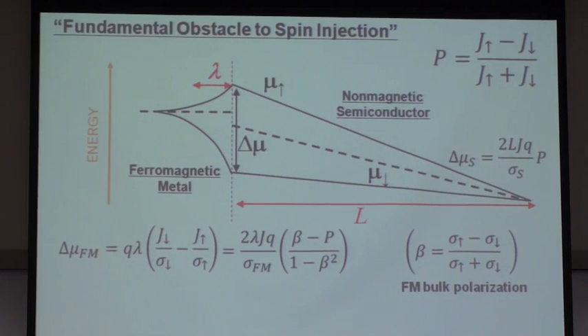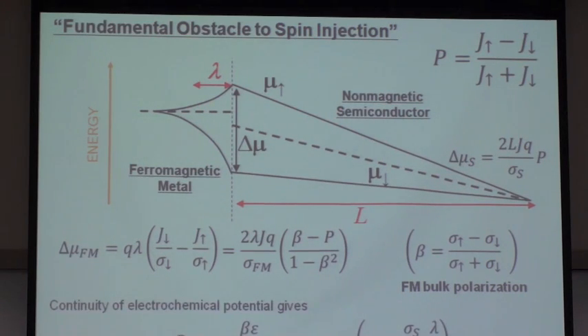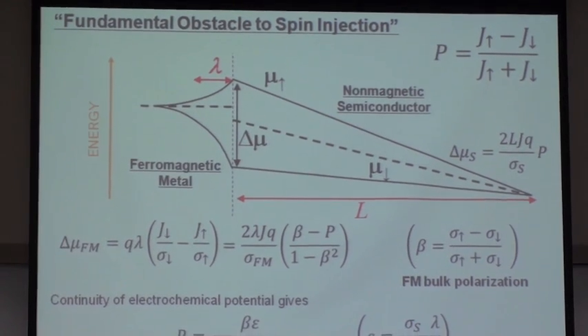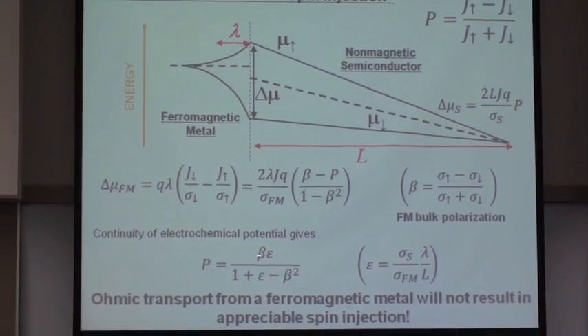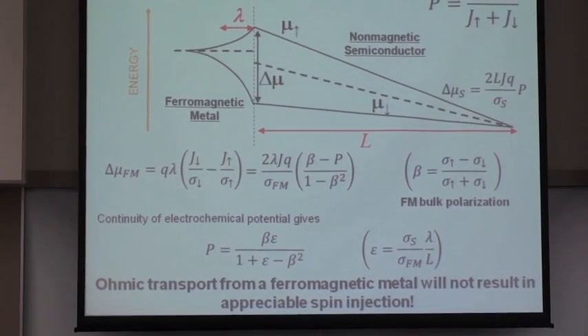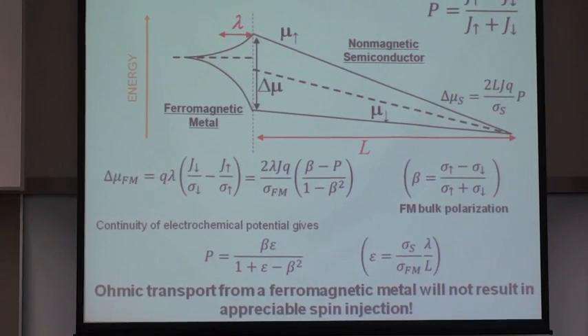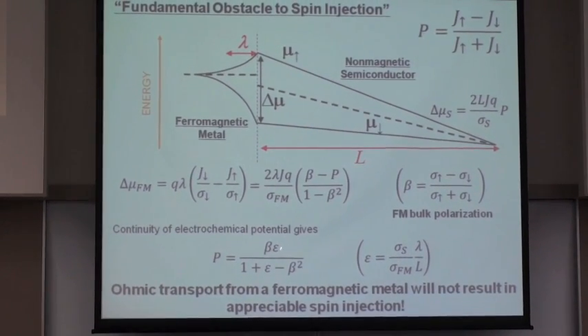And of course, again, because the splitting has to be equal across the interface, we set these two expressions equal to each other, and we can solve for the polarization in the current that's flowing in the non-magnetic semiconductor. So without doing all the arithmetic, this is the result. We see that it's proportional to the bulk polarization in the ferromagnet, which we expect, but the polarization is certainly not equal to the polarization in the ferromagnet. It's limited by this expression, epsilon, which is the ratio between not only the conductivities of the semiconductor and the ferromagnet, but also the length scales that are involved.